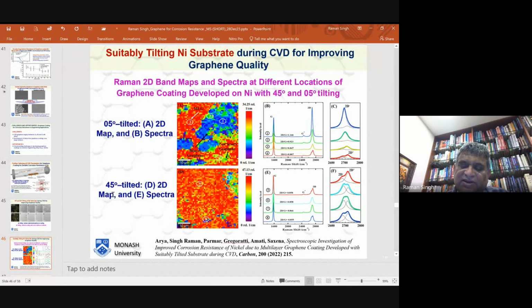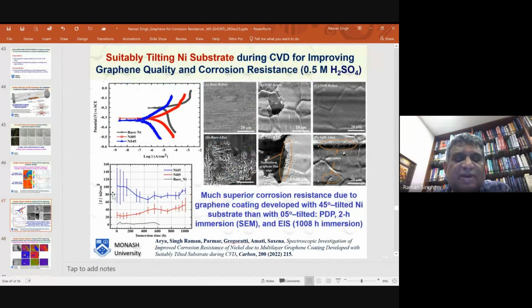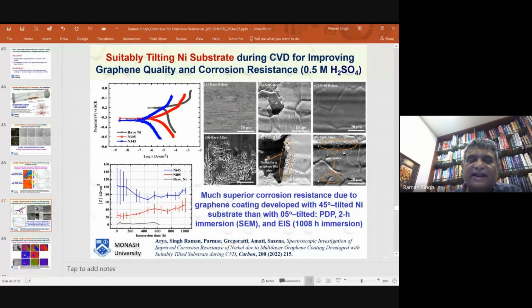So 45-degree tilted samples gave better corrosion resistance, and that was proved by electrochemical testing, as you can see, and also post-corrosion analysis. You can see the 45-degree tilted sample didn't have as much damage. It is in much better condition as compared to the 5-degree tilted sample, which underwent corrosion attack.